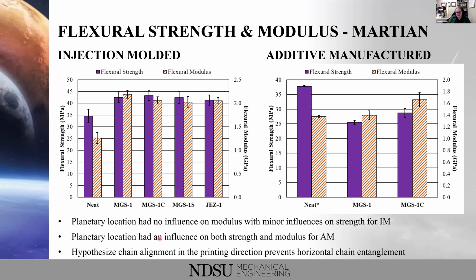There was an influence on both strength and modulus from the additive manufacturing side. Again, I think some of that might just come in inherently from the way we actually produce those parts. If we play a little bit more with some of those printing parameters, making sure we don't have voids within the part when we think it should be 100% infill, but there's actually some voids, we might be able to manipulate some of those material properties again.